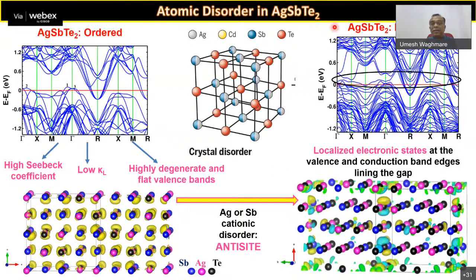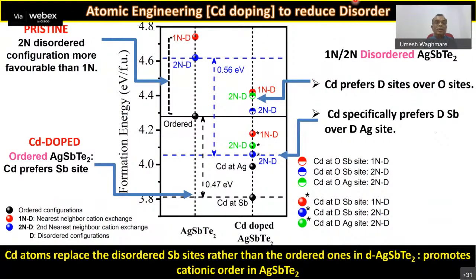So can we engineer this disorder in AgSbTe2? That's what we found and showed theoretically also: if you dope cadmium in AgSbTe2, it's interesting because of the size of cadmium and the charge of cadmium, it prefers disordered sites of antimony. Don't go into this complicated figure. There's a lot of information in it, but this is to convince you that the standard model calculations give you these formation energies, which allow you to tell whether a given doping will reduce disorder or increase disorder. And what we showed is that cadmium atoms replace disordered sites selectively, and hence improve the percentage of ordered sites.